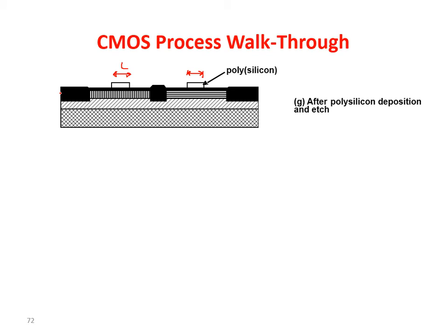Typically, you could do it in both ways, but actually what happens is that if you do the gate oxide at the beginning, all the processes that I've described up to here create some damage in the gate oxide. And then it is not so good at this point. So actually, the modern processes remove everything and redo the gate oxide in this position so that you have a very good quality of oxide. Okay, so it is not inconsistent. Actually, in the history of the technology, you have seen both things, but it's difficult that after all those steps, the quality of the gate oxide is still good at this point.